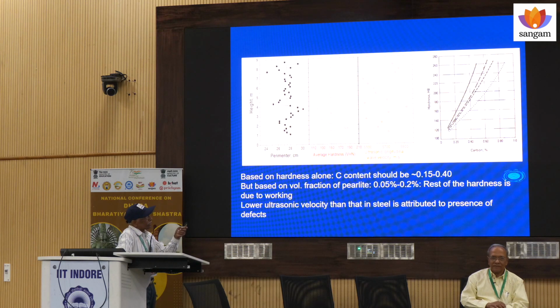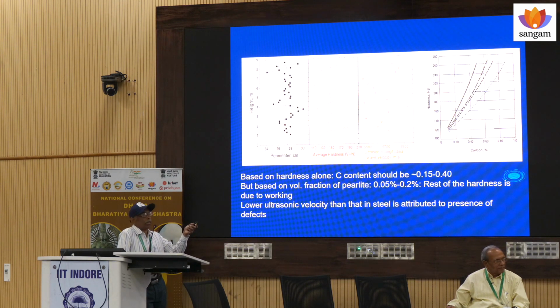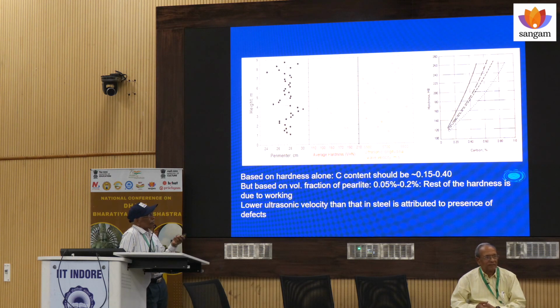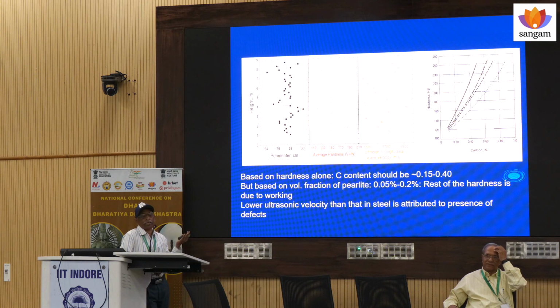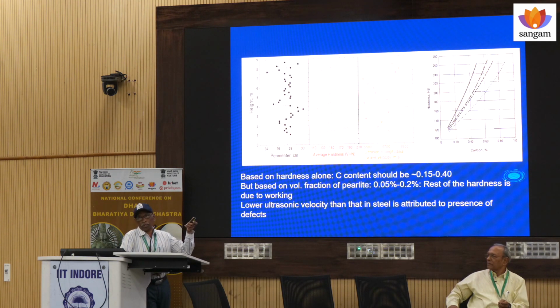And also if you see the ultrasonic longitudinal velocity which we have measured, because the cross section is small, we are able to use reasonably high frequency, and we obtained good ultrasonic velocity information. From this, we believe that for the given thickness, compared to the standard velocity in steel, the velocity we are getting is much less. That also accounts for a lot of voids, or the material is not continuous. But we did not do the radiography here because simple ultrasonics itself has given us the required information, and also we had only a certain time limit allowed by the Archaeological Survey of India to carry out these studies.